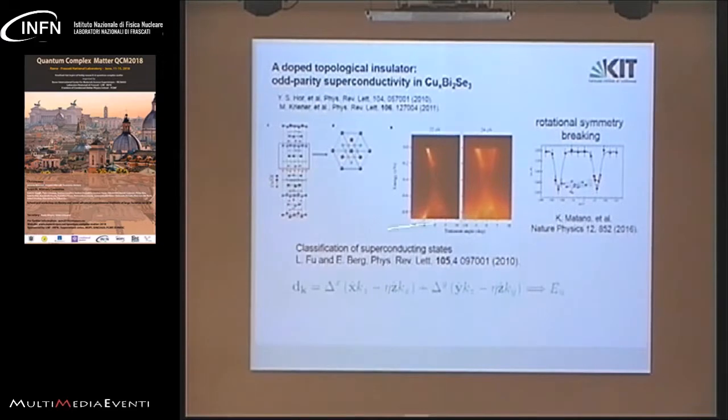One state that was proposed for the system is an odd parity state, once again, from Liang Fu and Venderbos, that has, again, a two-component order parameter. Now, because it's a hexagonal arrangement, you need to use a couple of coordinate transformations to get familiarized with what that potential state would be, but at the end of the day, it is straightforward. What was also seen is that the superconducting state breaks a twofold symmetry. This is Knight shift measurement data for different field directions in that superconducting state, and you see that the twofold symmetry is broken in that system.